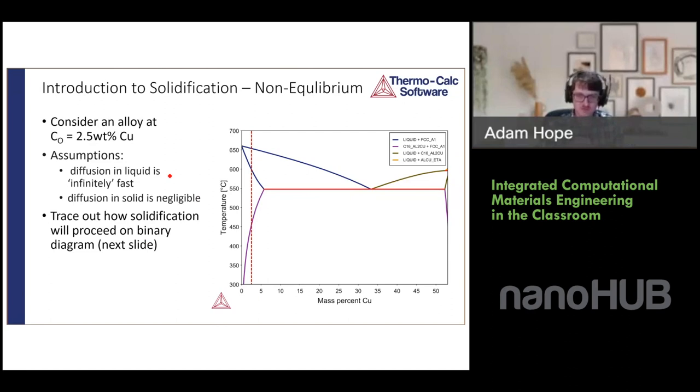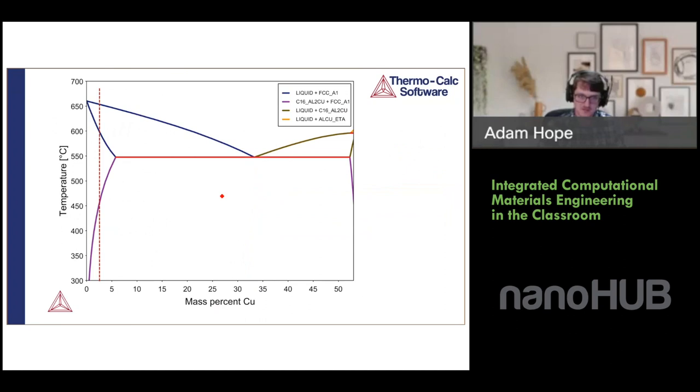And as long as the cooling rate isn't super, super slow, let's say it's 1 degree C per second or 10 or 100 degrees C per second, something like that, the time it takes us to first solidify, once we form solid, the diffusion in the solid is basically negligible, right? We don't have enough time for any appreciable diffusion if we're just talking about spending 10 or 20 seconds at 500-600 C. Okay, so let's, with those assumptions, trace out how we think solidification would proceed in the binary system,